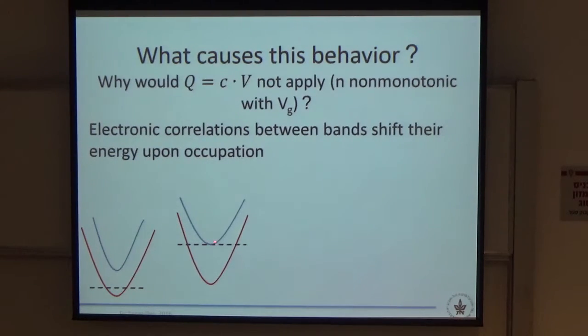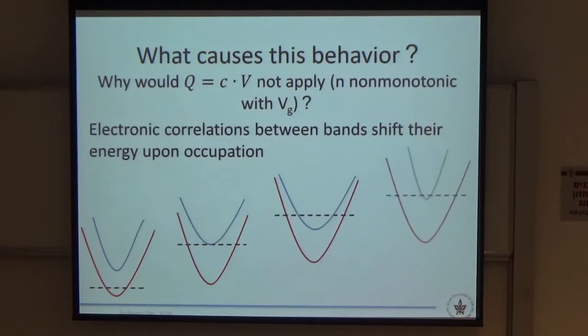And then you increase the chemical potential. Now this pushes this band away, and eventually you populate this band, but when you try to populate it more, actually it's favorable because of the high density of states here to pour carriers back into this band. So basically, the number of charge carriers in this band is non-monotonic, or if you want, the band structure is not rigid. It is changing when you change the chemical potential.